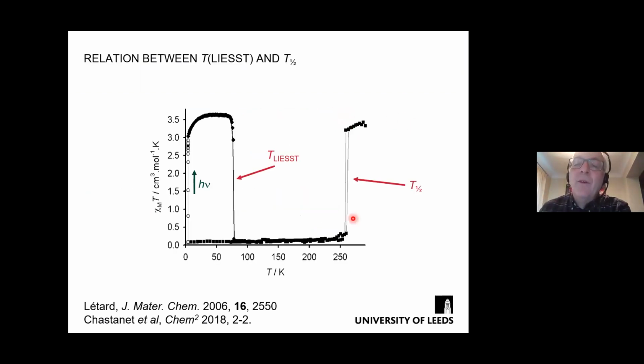So again, and I think we've seen this before, certainly in Dr. Mondal's talk this morning, maybe in Professor Sato's talk as well, that we can also induce a spin state change at low temperature by irradiation for an iron(II) complex. Usually you would use a green LED or a green laser to do this, which would work very well. Gives you a very nice low spin to high spin state change. And at sufficiently low temperature, the material remains trapped in its metastable excited high spin state. It's only when you rewarm the material, you reach a temperature at some point where now the lattice has enough thermal energy to be able to overcome the activation barrier for relaxation, and it collapses back to its thermodynamic low spin ground state at this temperature.